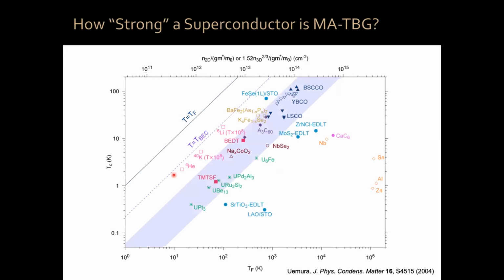But physicists do not compare the strength of a superconductor just based on TC. TC is very important, if nothing else, for applications. But the way you compare superconductors is by comparing how high TC is given how many electrons can contribute to the superconductivity in your system. This is usually shown in a log-log plot called an Uemura plot, where you have on one axis the critical temperature, and on the other axis the Fermi temperature in Kelvin, which is basically the density of electrons divided by some effective mass and some degeneracy. I have normalized it here so that you can put two-dimensional and three-dimensional systems in the same plot.